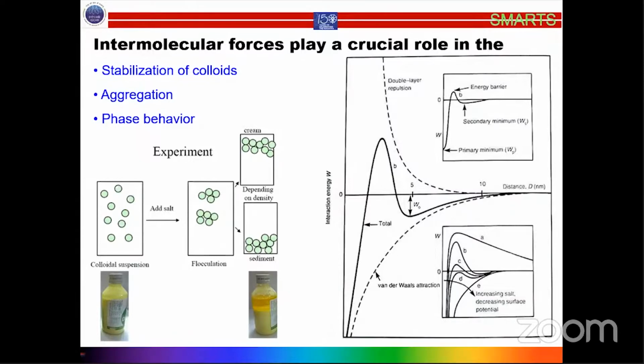If it is not very strong, what can happen is the particles will be able to cross this barrier. This is the sum of these forces. If the barrier height is high, then it's better, and particles will not be able to cross this barrier and reach the primary minimum. If they reach the primary minimum, you end up in a scenario like this: particles are flocculated or aggregated. If it is in the secondary minimum, it's not a major problem. You can provide some mechanical energy to get them back.